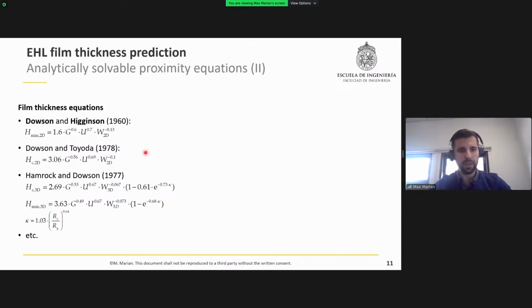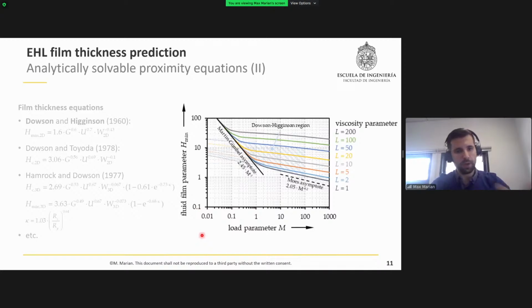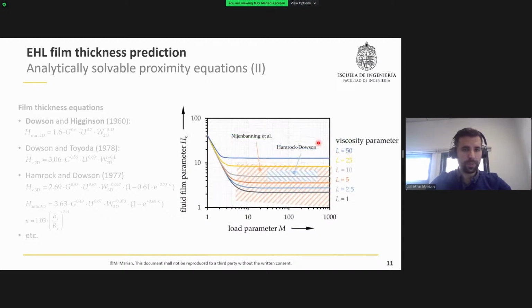Basically, due to the transformability of the aforementioned non-dimensional groups, you can also use the parameters suggested by Blok and Moes to calculate the EHL film thickness parameters. So basically, these are polynomial regression equations to estimate, for example, the minimum film thickness in dependency of the load parameter and the viscosity parameter. In this case, generally the minimum film thickness increases with a decreasing M and with an increasing L. And this would be some kind of curves for the central film thickness, which is less influenced for a wide range of the M parameters.